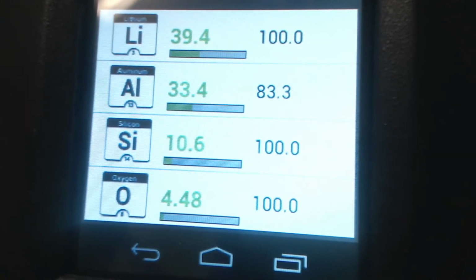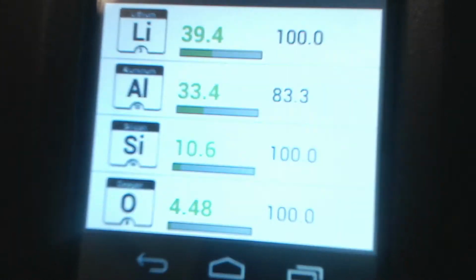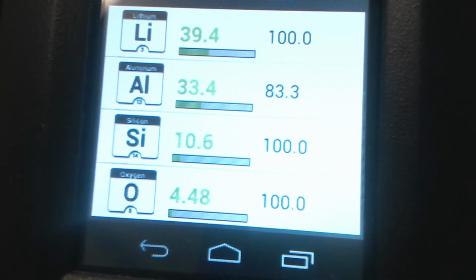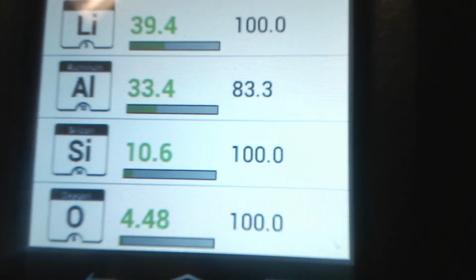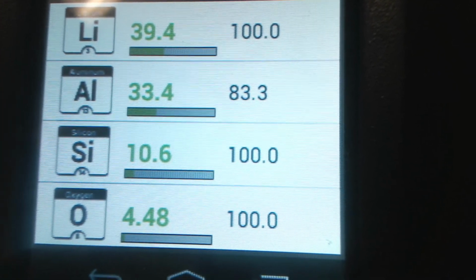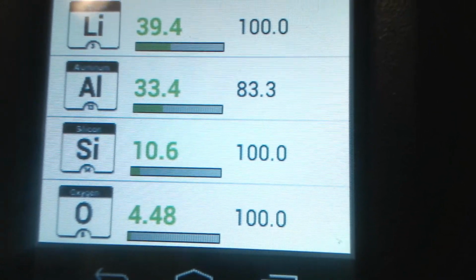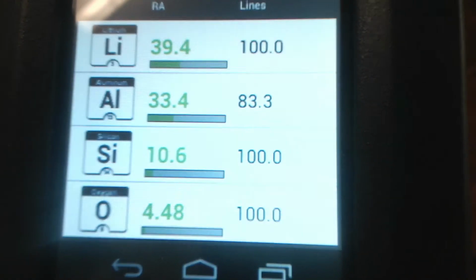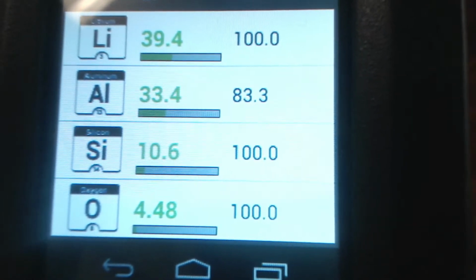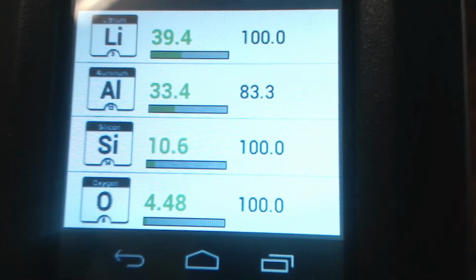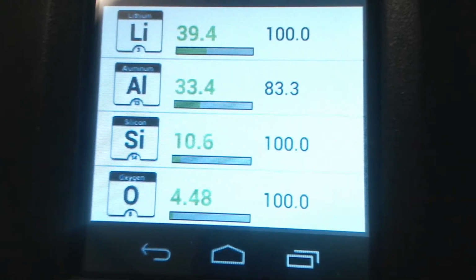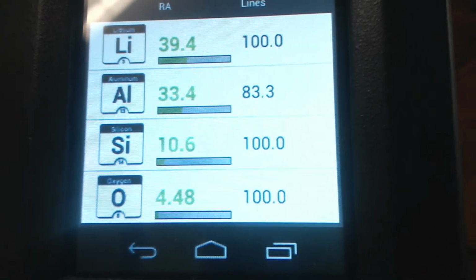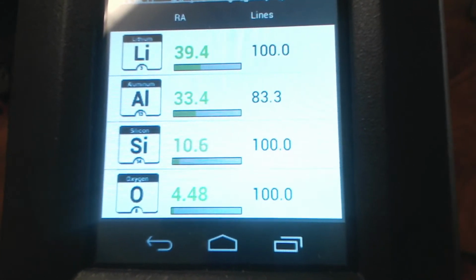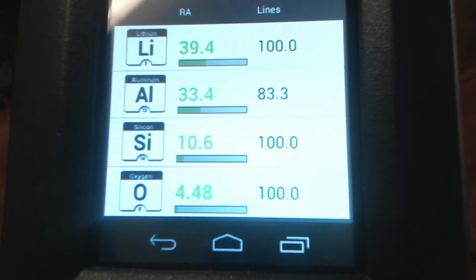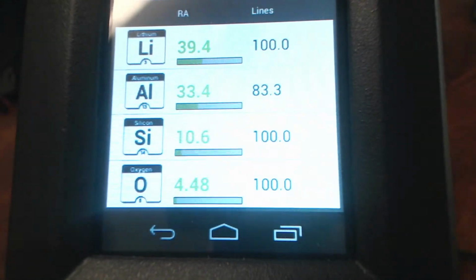All right, so this is actually a sample of a mineral called spodumene, which is a high lithium mineral. It also has a lot of aluminum and silicon. So that's why when we shoot it in this qualitative app called Element Pro, we see lithium, aluminum, silicon all at the top of the list of elements detected. You also see these green numbers. Those are not percentages. We call them relative abundances, but really they're just there to tell you how strong this signal is in the spectrum relative to the other elements in the spectrum. So it's not a percentage, but it can give you a rough idea if there's a lot or a little.